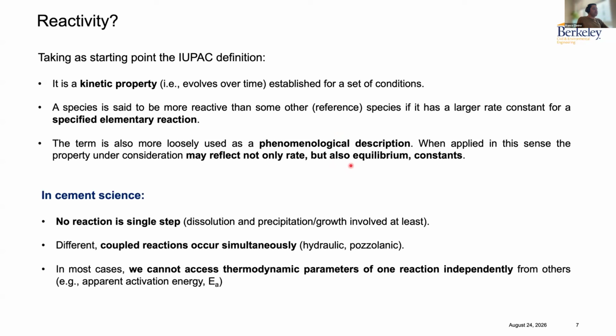So when we try to apply this to our case, we need to realize that in cement hydration, no reaction is single step based on the mechanistic definition that we just made, because we have at least dissolution and precipitation and growth involved in the formation of every hydrate. We have different coupled reactions that occur simultaneously. For example, all of the hydraulic reactions of clinker and the pozzolanic reaction or reactions of the different SCMs that we have in the system. And in most cases, we cannot access thermodynamic parameters of one reaction independently from others.